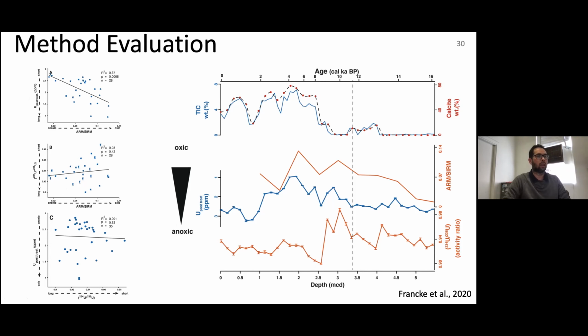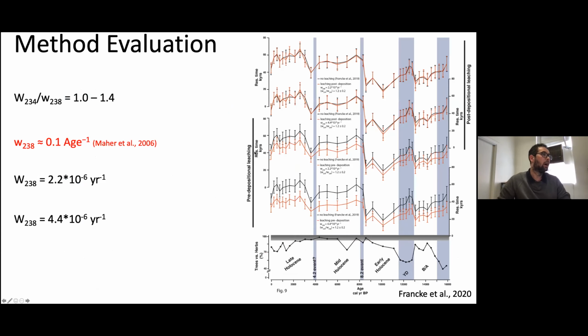And we can get an idea about the amplitude of the isotopic shift we would expect if the shift between uranium-234 and 238 would only be controlled by redox conditions. We can infer that by looking at the ratio between 234 and 238, and comparing these two records, the expected shift just related to redox is that the variability that we see in the Ohrid record here is 60-70 times higher than what you would expect if it were just redox induced. But to take that a step further, we can actually consider the preferential mobilization of uranium-234 in more oxic conditions in our estimates for the sediment residence time. And that's also what we tried here.